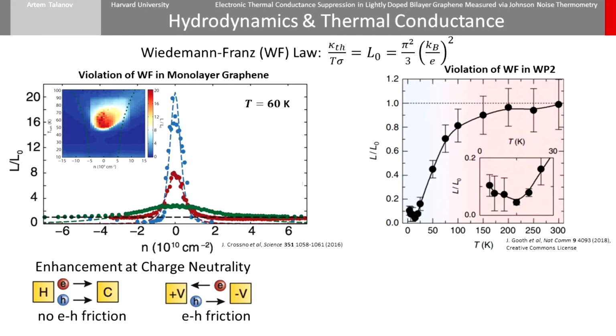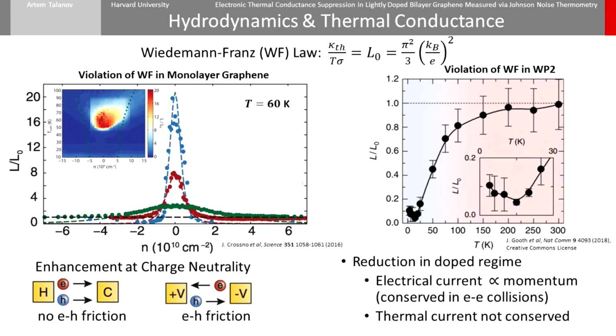In contrast to graphene, WP2, a semi-metal with separate electron and hole pockets, has been shown to have a strongly suppressed thermal conductivity due to hydrodynamics below 20 Kelvin. We can understand this by considering that collisions between charge carriers of the same sign conserve momentum and thus electrical current, in distinction from the electron-hole friction in monolayer graphene. Thermal current is not conserved in collisions of the same carriers.